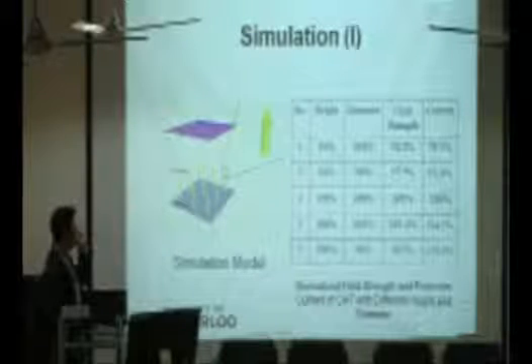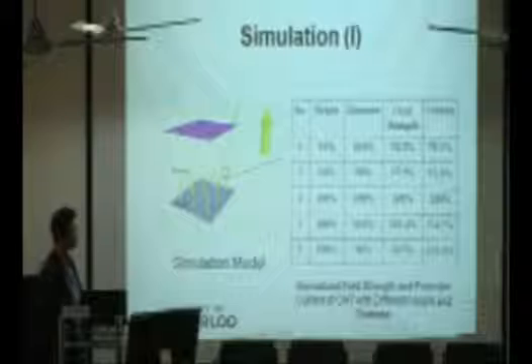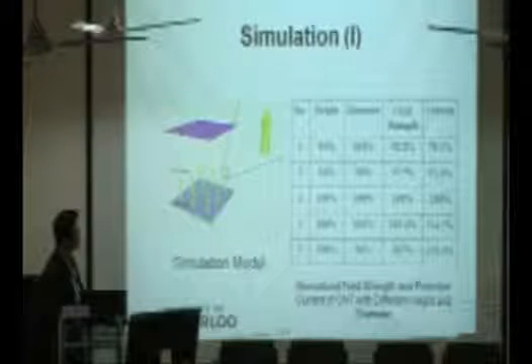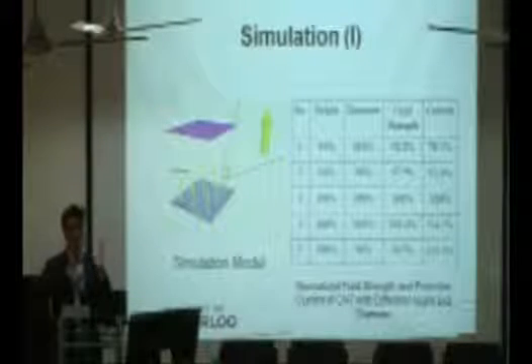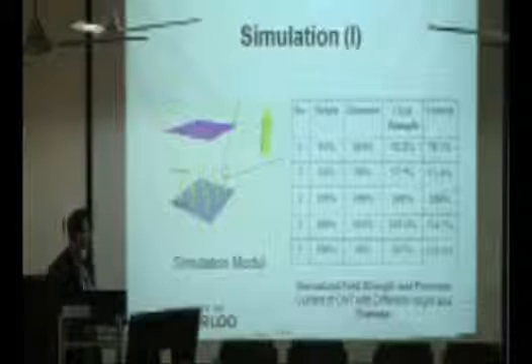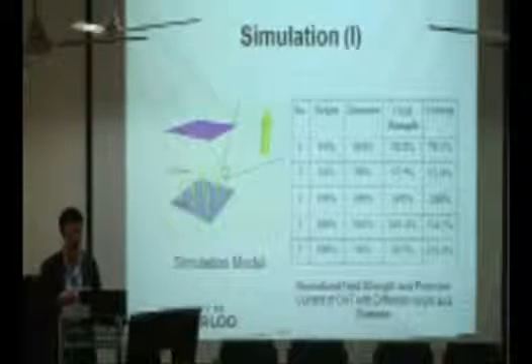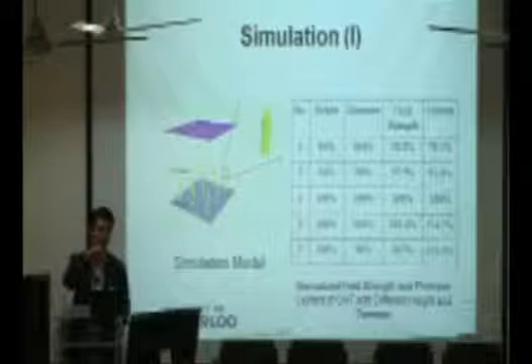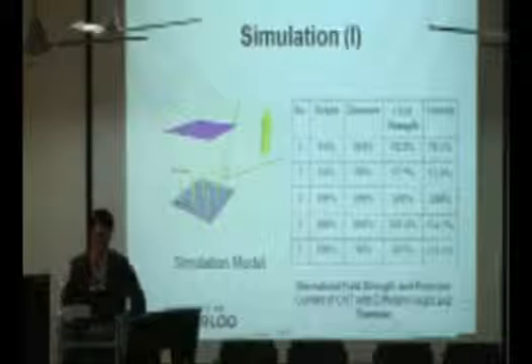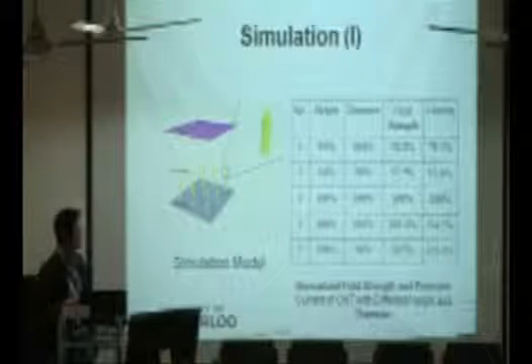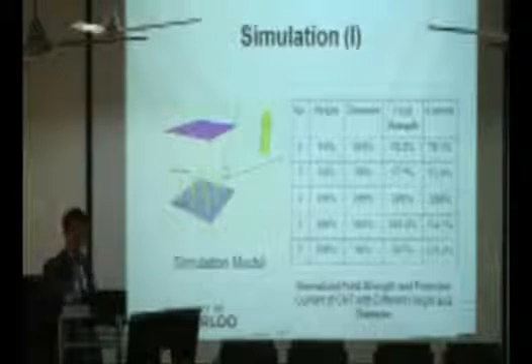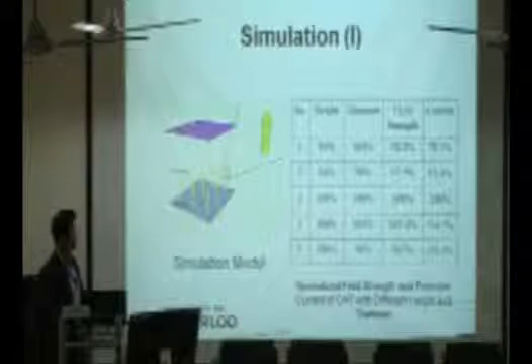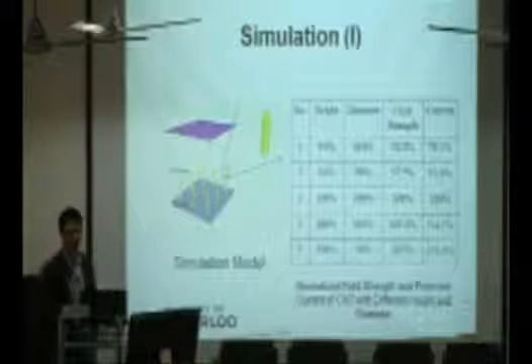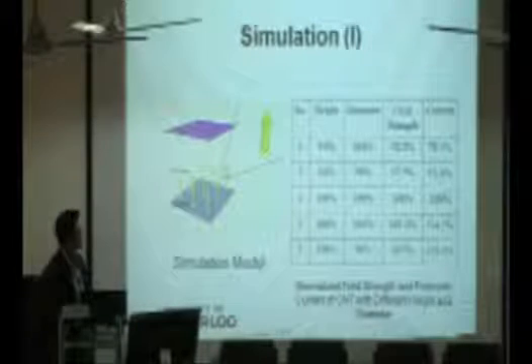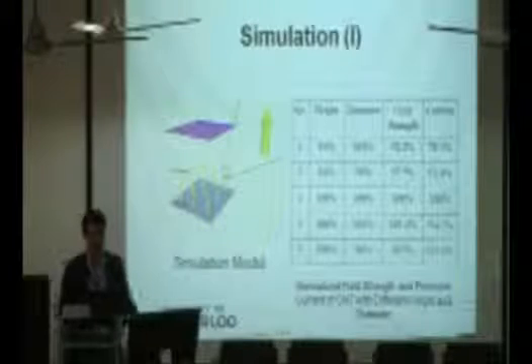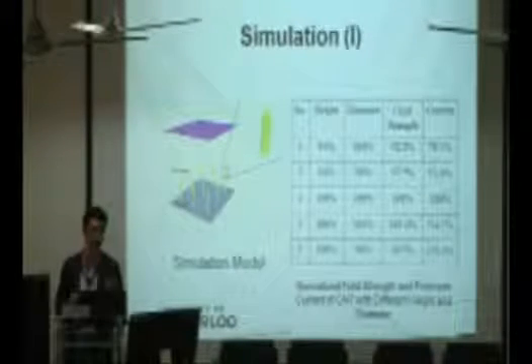So we have worked under the assumption that if a CNT array has a plus or minus 6% difference in height, and a plus or minus 4% difference in diameter. Given this really small difference in the height and diameter of the CNT, we want to know how much it would influence the current that we can extract from this 2D array of CNT. It turns out that it could be as much as 20%. So even if the height difference and the diameter difference is less than 6%, the current that we can generate could fluctuate as much as 20%.